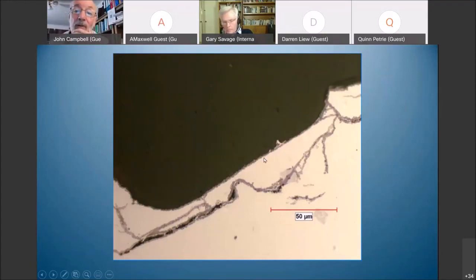crystallographically flat areas. So this is a kind of facet on the fracture, and these would have been facets if it had fractured here but didn't. But the fact that these are parallel tells you this is a bifilm. Now, it can't be that these are cracks by stress. These are not generated by stress, because once one crack is generated by stress, parallel cracks then can't form, because this is now stress relieved. The stress is dissipated by the first crack. A second and third cannot form. Whereas a bifilm doesn't care about that. It forms just because no stress is involved. So these are definitely bifilms.